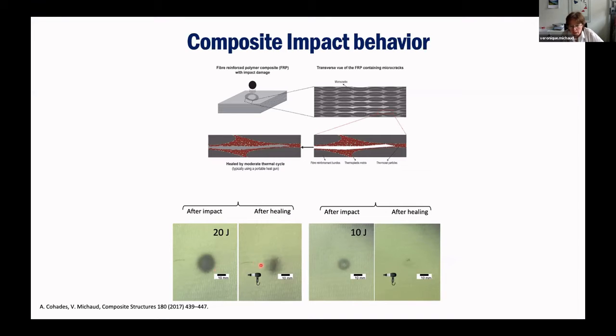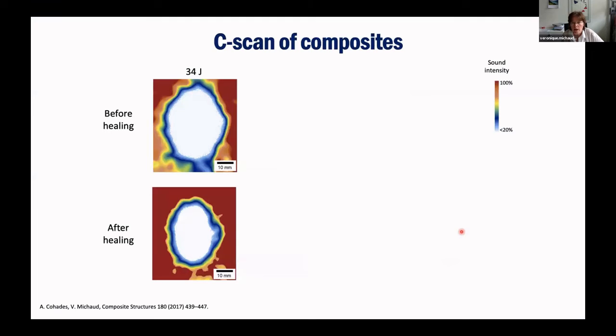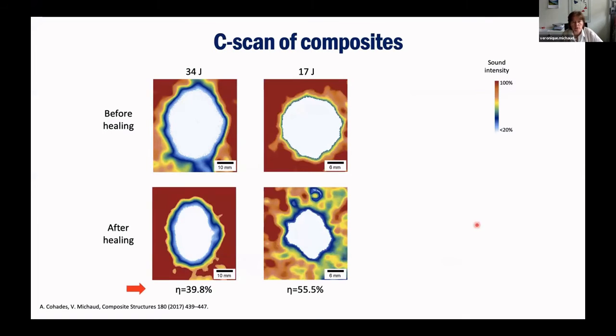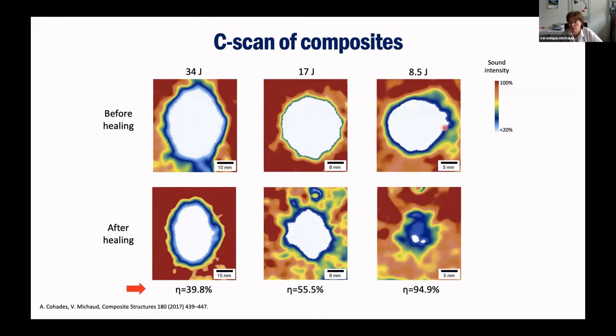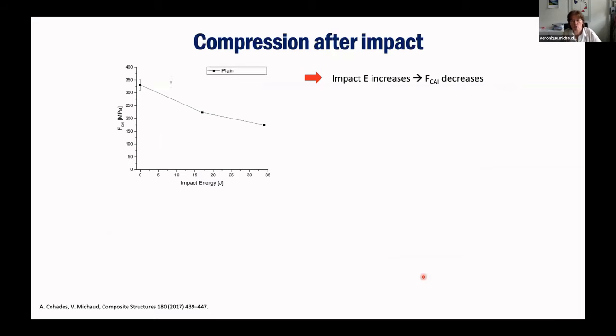So, of course, if we have broken fibers, we don't repair them, we repair only the matrix. We did a bit of C-scan. We see that after healing, so this is before and after healing, we have a good reduction of the size of the damage zone. And of course, we wanted to relate this to a mechanical test, and you all love compression in this crowd. So we also did compression, but mostly compression after impact, which is often used to test what happens after impact on the composite.